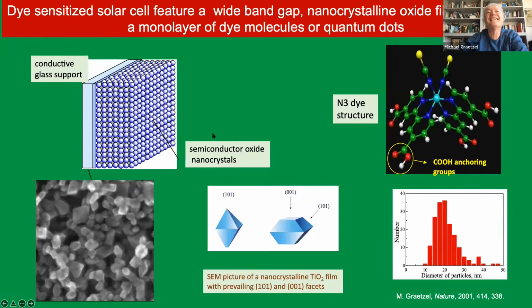Fortunately, it turns out that this approach is the right one to get the light absorbed and also collect the carriers. Because you might have questions: if you have a dye adsorbed on one of those nanoparticles and it injects after excitation an electron into the TiO2, what happens to this electron? Can you collect it over, say, several micron distance? Some people were very skeptical about this approach. And when we first found these extremely high photocurrents with these systems, they asked us to show proof. And for a while I was traveling with my own solar cells and showed the folks it was true. So it's a sensitized nanocrystal that is the light harvesting species in those films.